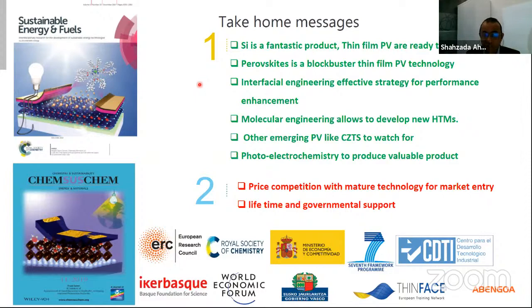Photoelectrolysis, yes, it has been done to produce hydrogen, and perovskite was used as a voltage source, because for splitting water you need 1.23 electron volt, and with the bromide-based perovskite you can easily achieve 1.5 electron volt. So this has also been done for photoelectrolysis to split water and produce hydrogen.